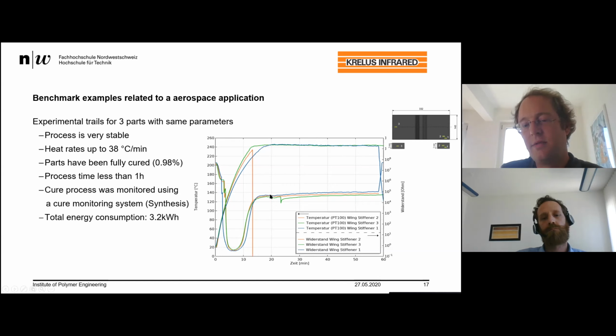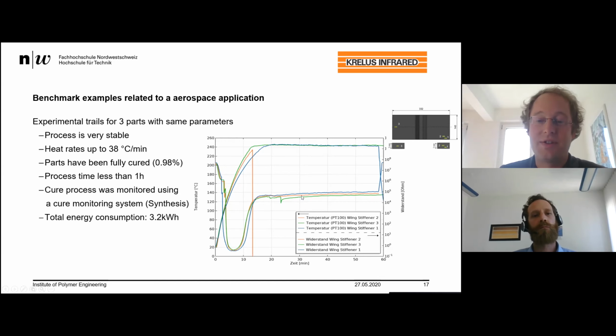And below you can see the curing process. And the strong advantage is that we can apply heat rates up to nearly 40 degrees per minute. So if you compare this to your autoclave, you're around 1 or 2 degrees per minute. So it's accelerating really fast. And so we're able to reduce the process time from 16 hours to nearly 1 hour, or you can see the curing process is nearly over after 30 minutes. So in our newest trials, we applied just 30 minutes.